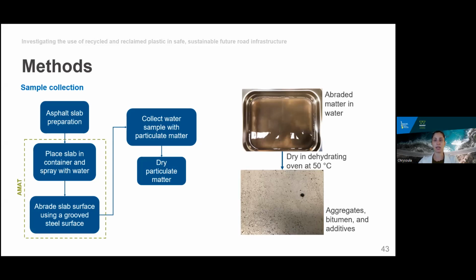After abrasion, the slabs were rinsed with water to wash off all captured particulate matter, and the contaminated water was collected in trays, and you can see those trays here to the right. The water was then evaporated in a dehydrating oven at 50 degrees Celsius, and the particulate matter was collected. As only particles smaller than 5 millimeters can be classified as microplastics, the particulate matter was sieved and only particles of smaller size were used for this analysis.